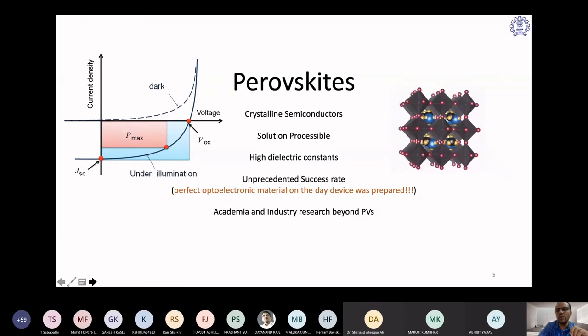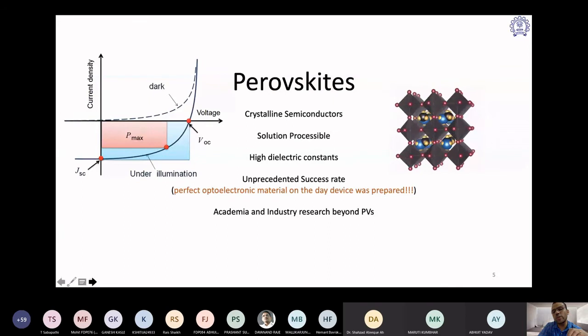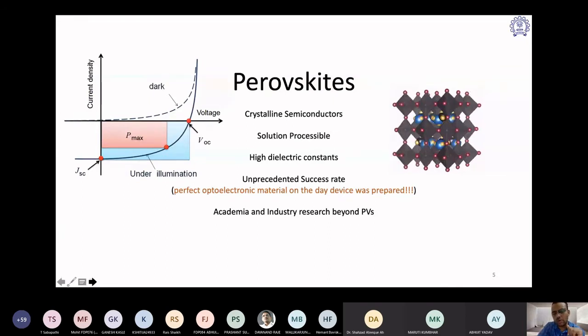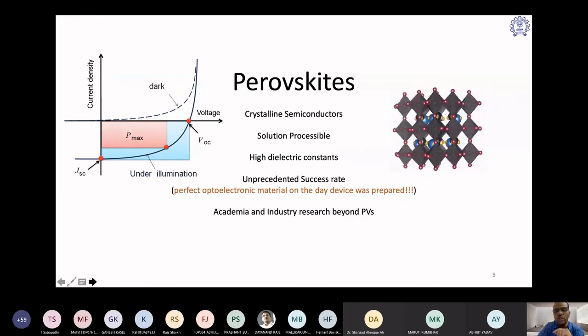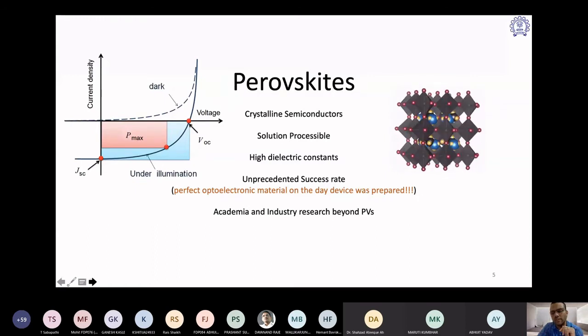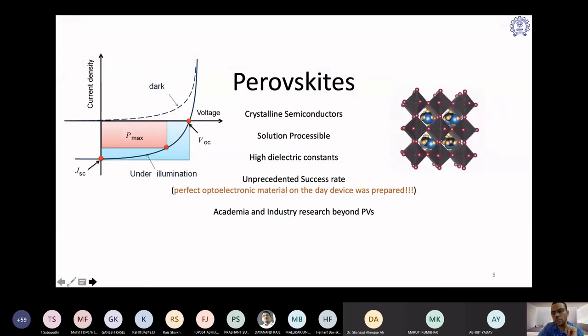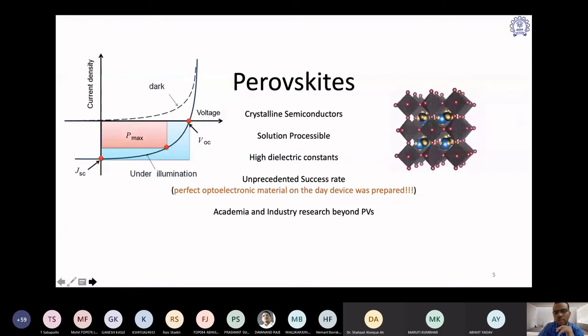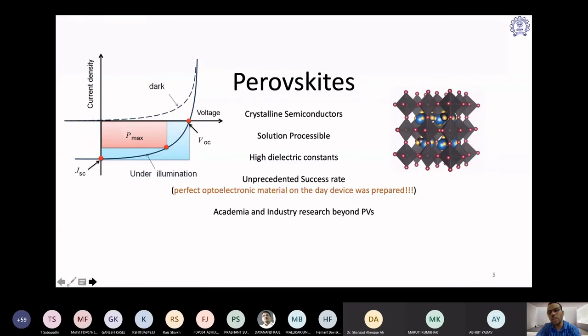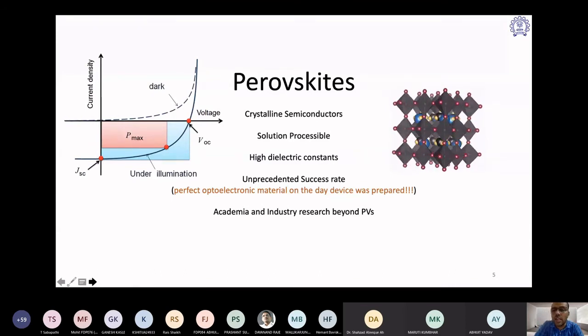You can make a zinc oxide film also by the solution process, but if you make the zinc oxide by sputtering, you get much better crystalline properties. But with these perovskites, as I was telling at the start of my talk, you have the organic salt, you have the inorganic salt, you put them in the same pot, and you go for a tea, and you come back and you have already formed the perovskite. That will not happen with oxide perovskites like zinc oxide, titanium dioxide, or any kind of ABO3 family perovskite such as barium titanate, lithium niobate. But this happens in this halide perovskite.